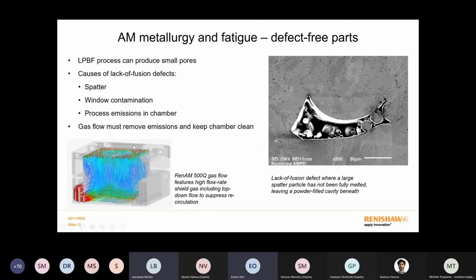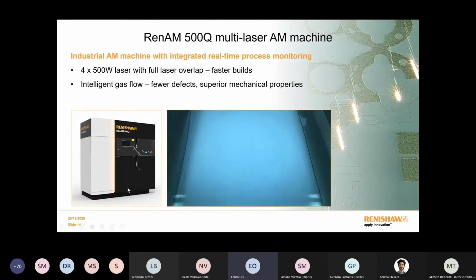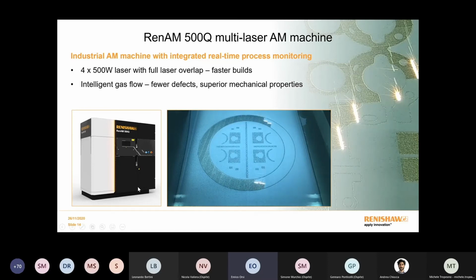Most of these defects will be cured by a good gas flow. Here you see the result of a simulation of the gas flow that moves argon gas vertically in the chamber and then horizontally to remove it from the chamber. Our main production machine is a machine with 4 lasers. Here you can see a video of the 4 lasers operating at the same time on a single part. This machine will greatly improve the productivity. However, it also poses a lot of challenges to achieve a good gas flow that removes all the particulate from the chamber.